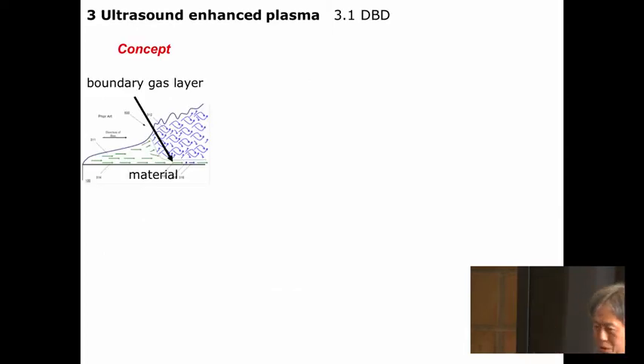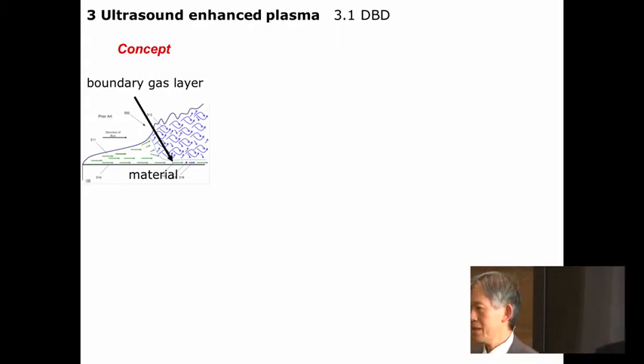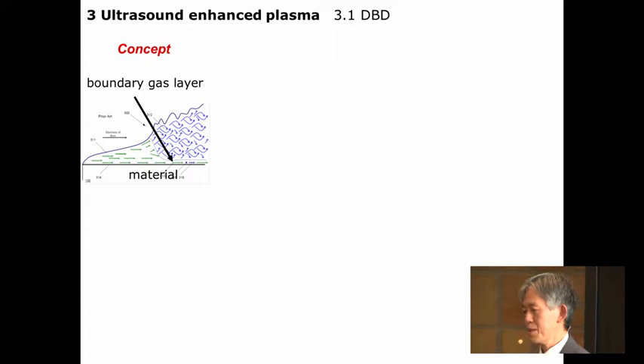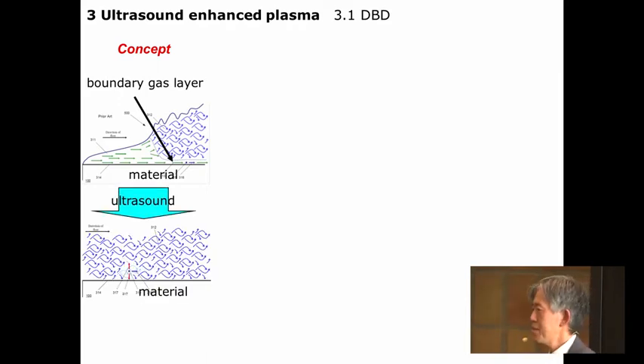But then I also want to shortly explain the second big topic about ultrasound enhanced plasma. The idea is that if you want to treat material using a plasma, you want to generate a plasma above the specimen, but then there is typically a sticky gas boundary layer on the surface, which can disturb efficient treatment. If we can remove it or reduce the thickness, that would be probably better. Then it can probably be achieved by introducing acoustic energy from the top. That's the idea.